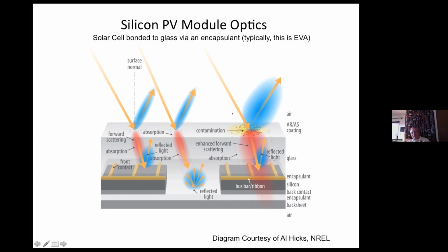Now, imagine in your mind what happens when you have contamination. You have this extra reflection. Each one of these would then be a vector in a particular direction. It's scattering the light, so you're losing this light more. You have enhanced scattering, forward scattering, which might be a good thing because the solar cell can still collect it. But you have perhaps more absorption within the module, reflected light, and it goes on to bounce again and again. So you can see that if you really wanted to model the effects of soiling due to contamination, the situation would be somewhat complicated, wouldn't it? So we do these things at least initially empirically.